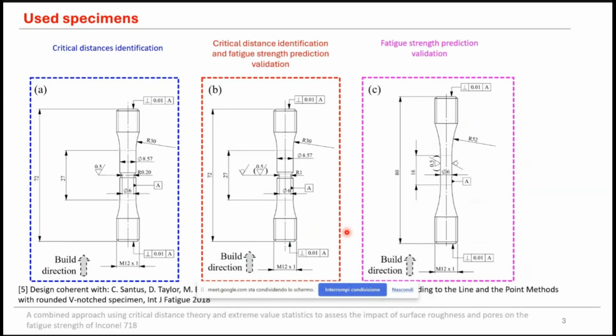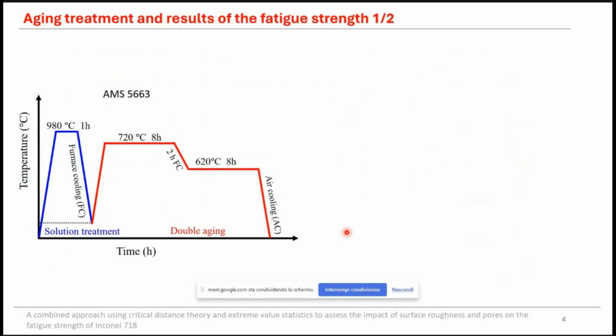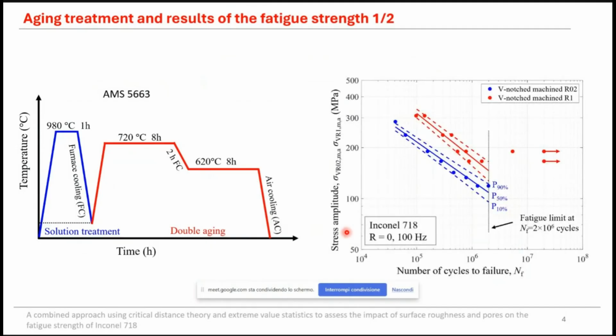The design of the specimens was coherent with the reference reported here for the identification of the critical distance. The specimens underwent an aging treatment coherent with the AMS 5663 to increase the surface hardness with respect to the base material. Then we performed the fatigue test with a load ratio equal to 0. The fatigue limit was fixed at 2 million cycles because of previous research of the group.